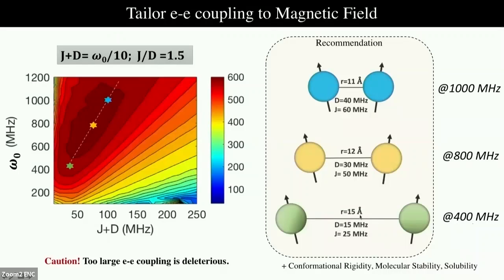If we are going to higher magnetic field, for example 1 gigahertz, the coupling has to become stronger, but the balance between J and dipolar coupling has to be maintained. If we follow these two constraints, then it's possible to have effective cross-effect DNP even at a very high magnetic field of 1.2 gigahertz. But the caution that I would like to mention is that the coupling should not become too large. If it becomes too large, then we reduce the polarization difference between the two electrons.